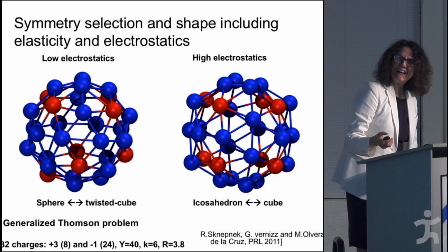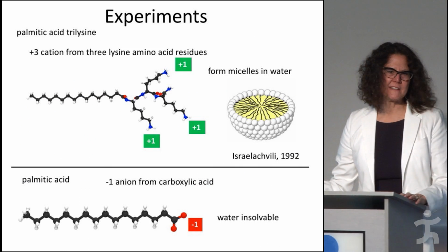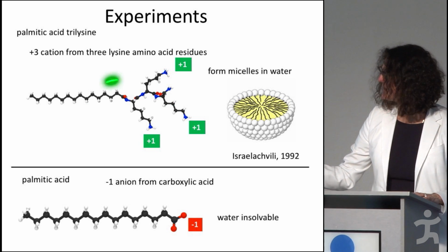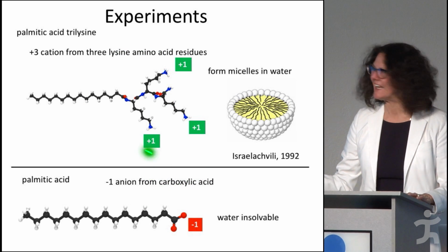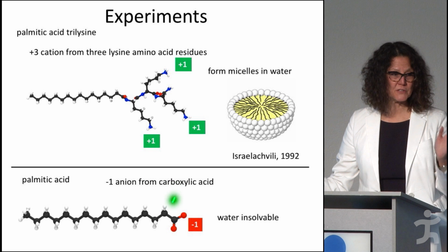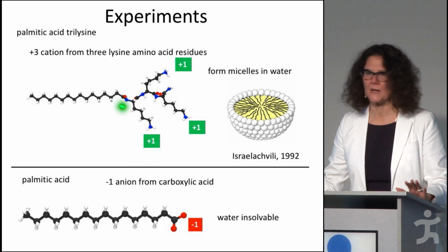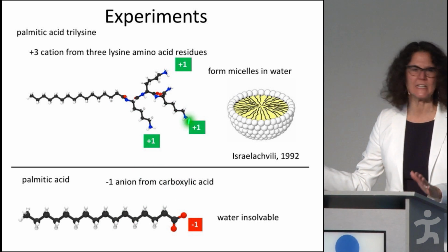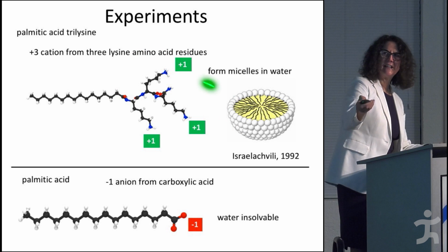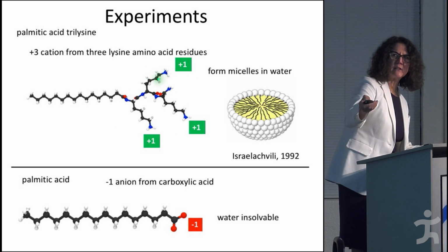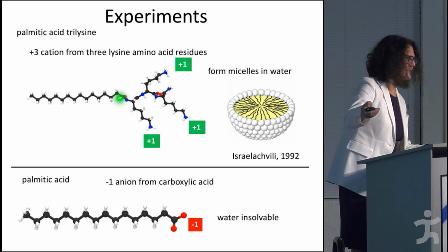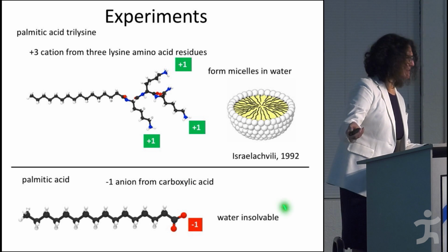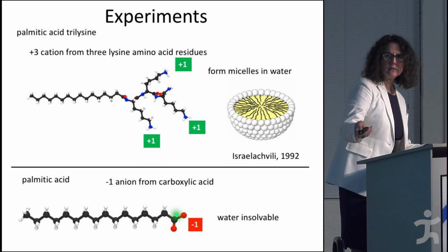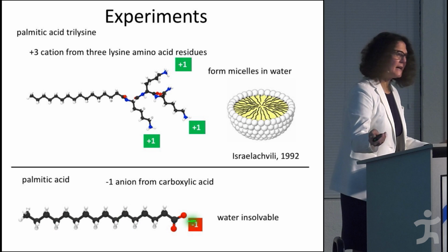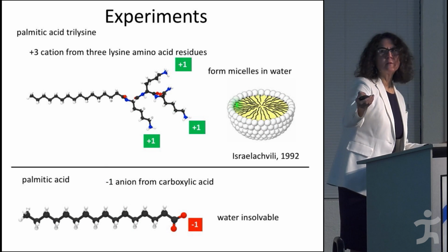And so now I'm going to describe the things designed in the experiment and show you the shapes that we get, and the changes they can go through when you change what we call the ionic strength, the pH of the solution. So these can dissociate one charge or 3 charges, and this one can dissociate -1. This molecule doesn't go into water because it's so hydrophobic, and this one forms micelles.